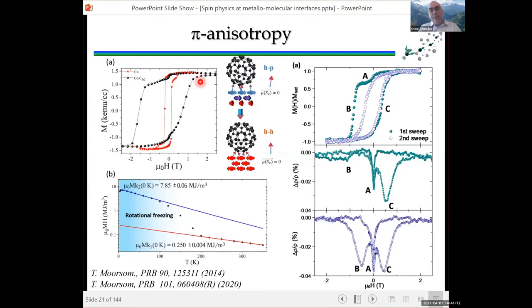And that can be seen also in AMR measurements, where you can see that this first reversal doesn't have a peak because we are not forming domains. It's a coherent change in the magnetization due to rotation of the molecule. And then once that is destroyed, then we can see the AMR peak emerging again.